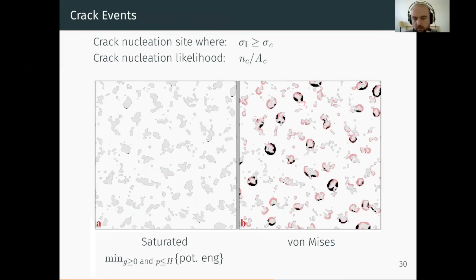To do this, I did a set of rough surface contact simulations, where on each simulation, I look at the principal tensile stress at the surface. And I look at zones where the principal tensile stress is larger than the critical stress for crack nucleation. I did two sets of simulations. I did a set of simulations with a full description of plasticity, with von Mises plasticity in this case, using the method I described to you. And I did also a set of simulations using this elastic contact with added hardness condition. This is what I call saturated plasticity.